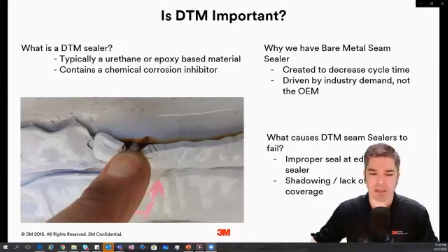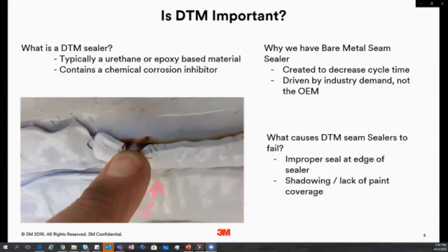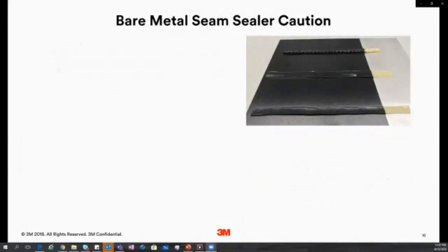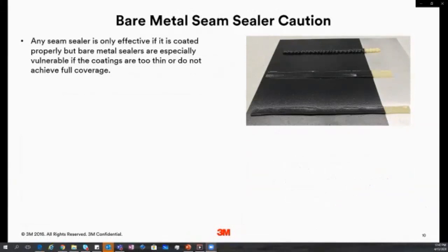By going out and taking a look at it up close, we were able to determine that it wasn't necessarily the product that had failed, it was more so the application. And that's where the concern comes in with direct-to-metal seam sealers: we really have to be hyper-focused on the application. Not just the seam sealer to the surface of the vehicle, but we have to be concerned about the top coats that we're applying onto the surface of these as well, right? So if you're using a bare metal seam sealer, and especially on the edges, it's only going to be as effective as the coating that you're putting over the top of it, right? And so this is where I want to point out that no matter what coating you're using, most likely a paint manufacturer's epoxy primer or a urethane coating, we just want to make sure that you're always following the product manufacturer's recommendations for application.